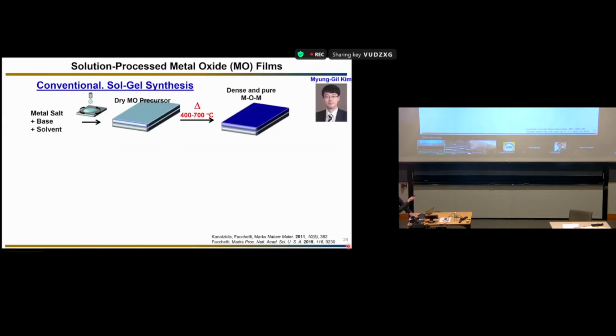So what is the typical way to prepare a solution oxide? There are many ways, and we know quite a lot about that. When we started this project, I think it was 2008, something like that. The most classical way to do it is, for example, you want to make an oxide which is indium oxide. So you have indium as a metal. You start from, I don't know, indium chloride or indium nitrate. In a solvent, you dissolve it, sometimes you put in a little base, a little ammonia or whatever, and you spin coat, and then usually you get a dry film, which is a big mess, and then you anneal, you burn off everything, at 400 to 700 degrees, and you get the indium oxide. So this is the classical way to do it.